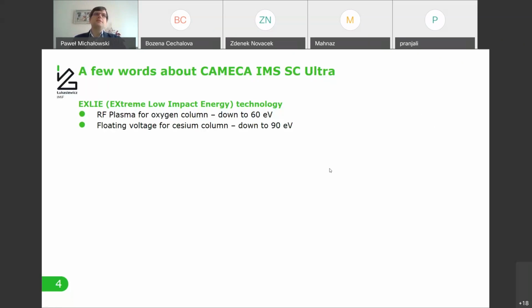So because typically when you start decreasing the acceleration voltage, you may get problems to obtain a good quality beam because of the electrostatic interactions. Primary ions will repel, and then the focusing of such a beam is very challenging. But in here, CAMECA used a very nice approach. So basically, instead of decreasing the acceleration voltage, I can keep it quite high, even more than 1 kV. But I apply additional floating voltage to the column itself, so I can gradually decelerate these ions, so that in the end, I can decrease the impact energy of these ions down to 90 eV.